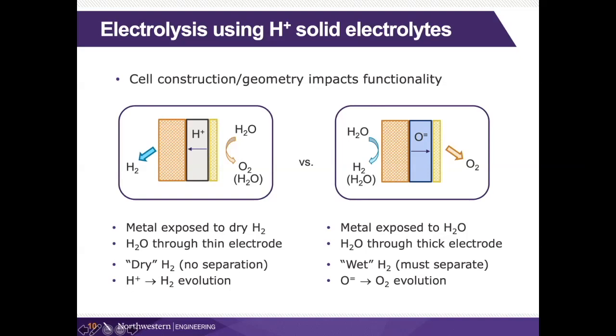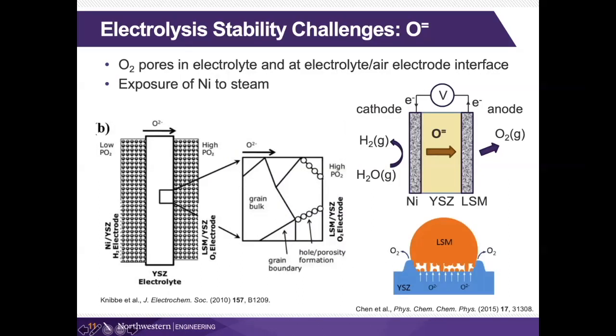It's not so dramatic, but it is a disadvantage. From the electrocatalysis perspective, this is much better because hydrogen evolution is really very easy. Here you have to do oxygen ions coming out and becoming neutral oxygen species at the air electrode. And to show you what that looks like, the consequence of that in the oxygen ion conducting system, because this overpotential is large, you build up a very high effective oxygen partial pressure in the electrolyte. And at this interface, you start to create some oxygen bubbles, even in the electrolyte, but certainly at that interface. So this has been a real challenge to have high stability for the oxygen ion conducting systems.